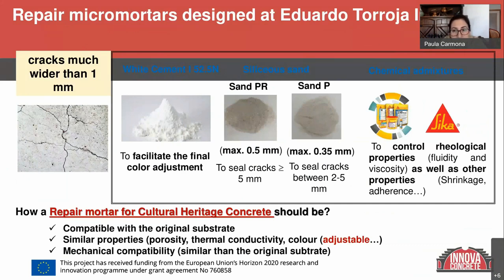it was introduced yesterday by our colleague Ines García Lodeiro. It is the repair micromortar that is aimed at filling cracks wider than 2 millimeters and even 5 millimeters, depending on the type of sand, as you can see here in the slide. The material was designed to be compatible with the original substrate, this concrete, with similar properties, not only porosity, but thermal conductivity and also the mechanical properties. The color was originally white, but it can be adjusted to specific cases with pigments. Next, please.